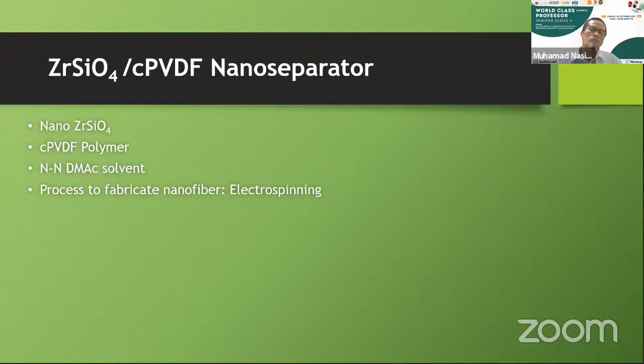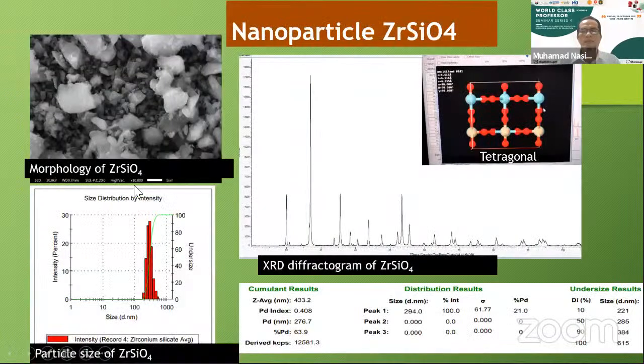And then, based on this, we develop the zirconia silicate co-PVDF nanofiber. We use nano zirconia, co-PVDF, and DMAc solvent. This is a basic characteristic of the material we use. This is the morphology of zirconia silicate. We measure the particle size. The particle size is around 300 nanometer.